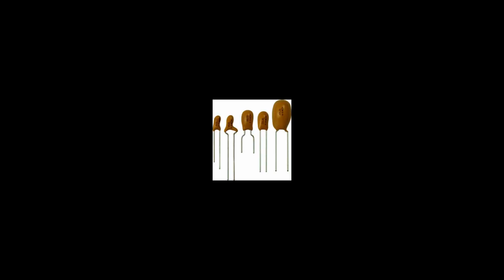In solid tantalum electrolytic capacitors, the heat generated by the ripple current influences the reliability of the capacitors. Exceeding the limit tends to result in catastrophic failures with shorts and burning components. Current surge, picopulse current. Solid tantalum electrolytic capacitors can be damaged by surge or picopulse currents. Tantalum capacitors which are exposed to surge or picopulse currents should be used with a voltage rating up to 70% in highly inductive circuits. If possible, the voltage profile should be a ramp turn-on, as this reduces the peak current seen by the capacitor.